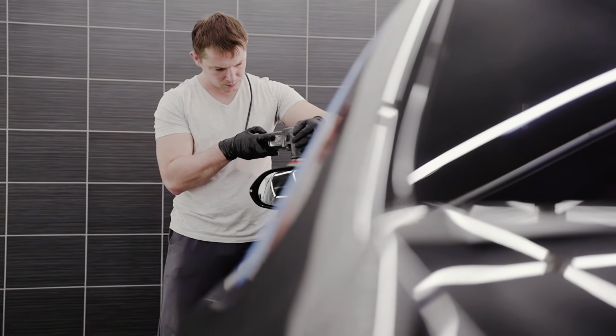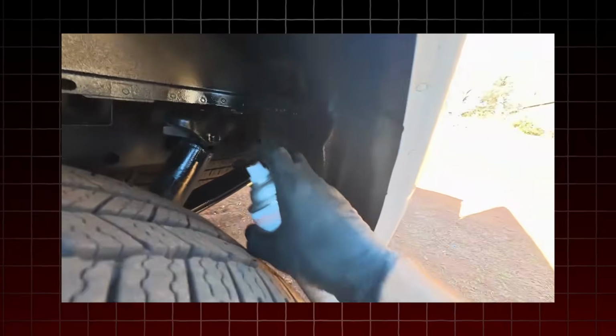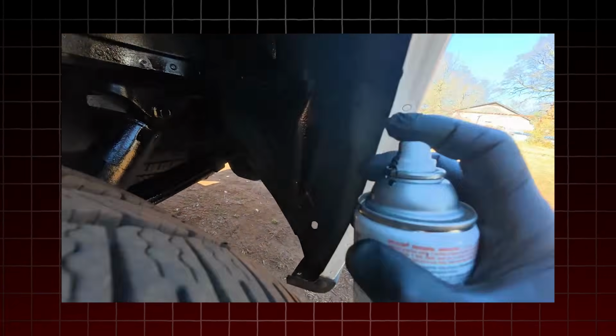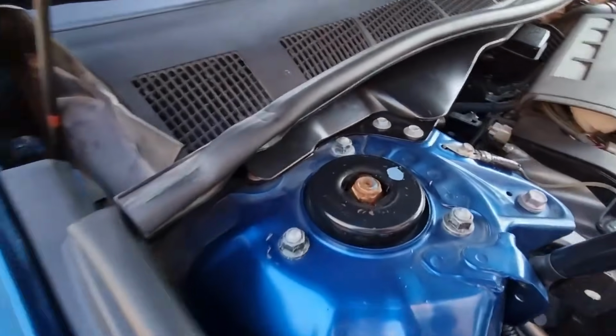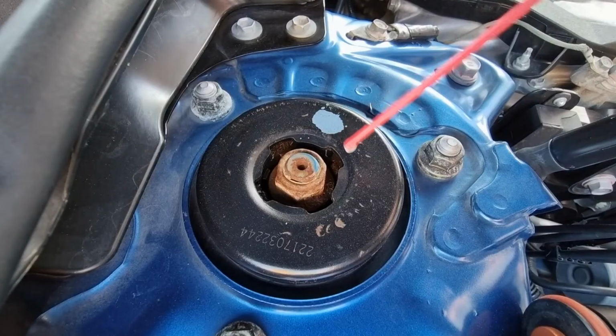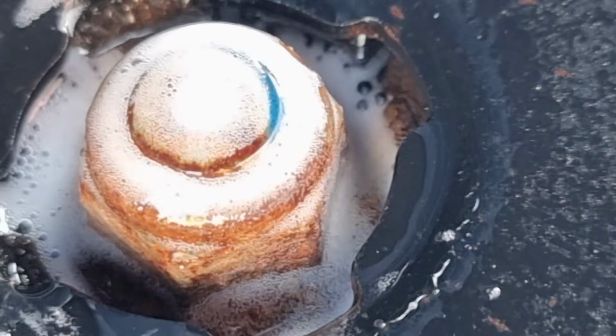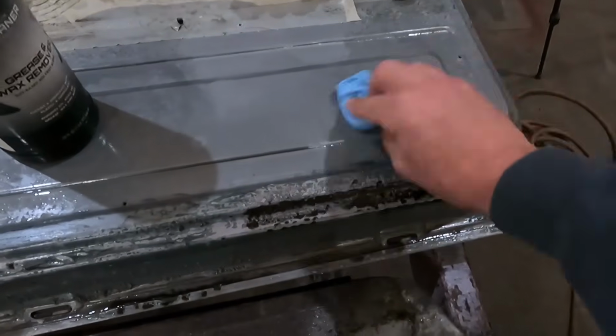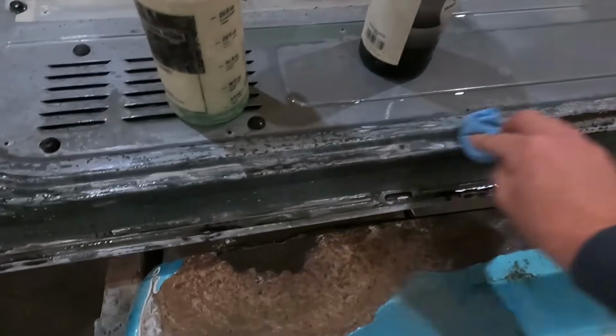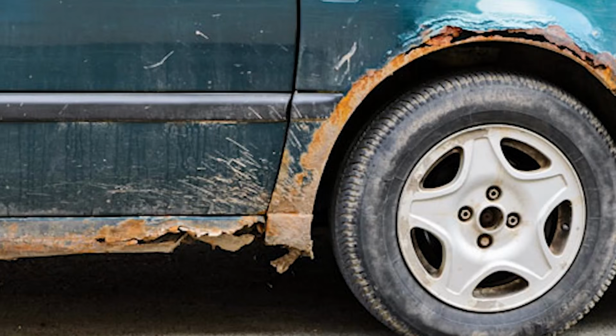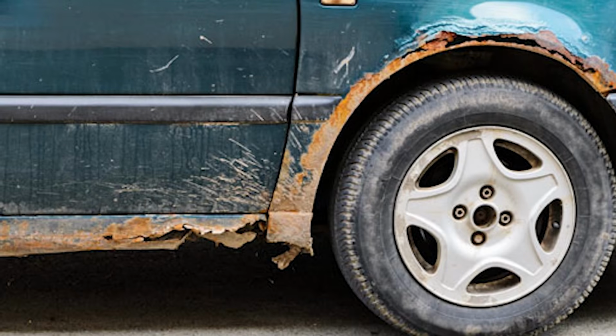Drivers who skip the neutralization step and apply top coat directly over Ospho-treated surfaces experience primer delamination within weeks. The delaminated primer exposes the treated metal to moisture. The rust resumes. The treatment appears to have failed when the product chemistry was actually adequate. The neutralization step was what failed.